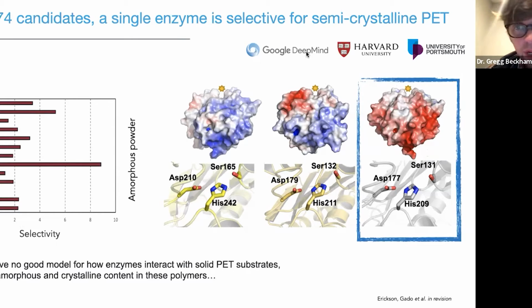which we solved, this was before AlphaFold 2 came out. We solved this with Google DeepMind. We sent them all 74 structures on a Friday, and they sent us all structures back on a Monday morning. This enzyme has a higher surface charge, the one that's able to act on crystalline PET. We don't know if that's the reason why this is better, but we're currently working with Harvard University, the University of Portsmouth, and not shown here, the University of Manchester, to do directed evolution on this crystalline active enzyme to attempt to understand the reasons why it is active on crystalline substrates. And so that's quite cool, and this is a nice discovery, we think.